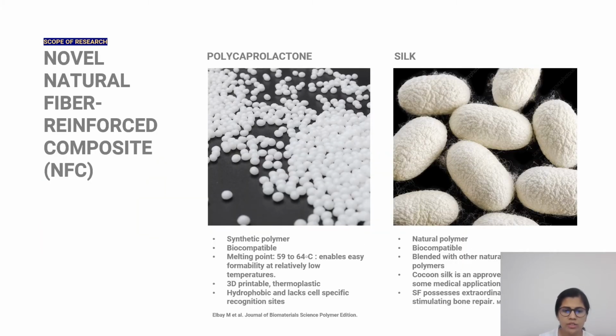So the scope of the research is to develop a novel natural fiber reinforced composite. In our study, we have utilized silk fibroin microfibers and have reinforced these microfibers into the PCL matrix. The justification for using these two input materials is that PCL, which is polycaprolactone, a synthetic polymer, is biocompatible, has a low melting temperature of about 59 to 64 degrees centigrade so that it can be processed at low temperatures. It is 3D printable as it is thermoplastic, but the drawback here is that it is hydrophobic and it lacks cell-specific recognition sites.